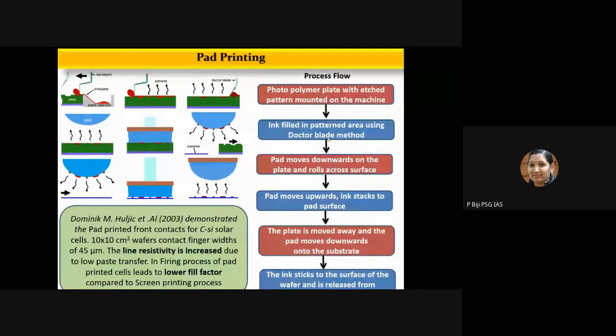Then after that, the solvents in the paste will start to evaporate, and the surface becomes a little bit tacky. Then the pad moves downwards onto the plate and rolls across its surface. So you can see that it is a roundish surface. This rounded surface of the pad is important as it prevents air from being trapped between the pad and the plate surface. So when the pad moves upwards, some of the ink sticks to the surface. At this point, some of the solvents evaporate from the surface of the paste, which adheres to the pad, making this surface a little bit sticky.